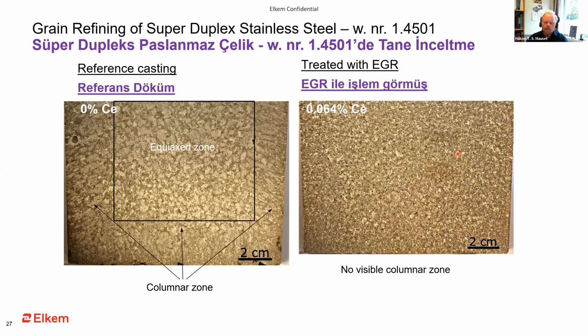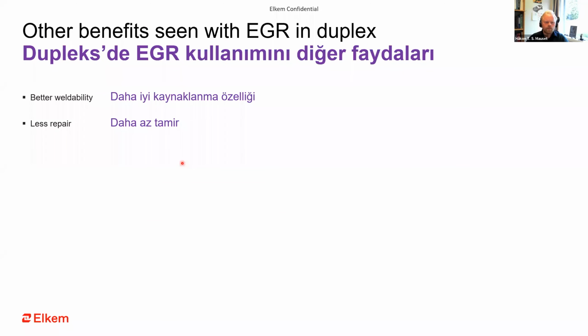While this is the one treated with EGR. Here you see we have 640 ppm of cerium in the steel, and there is really no visible columnar zone here. The equiaxed grains are much smaller than this one. So other benefits we've seen with EGR in duplex are better weldability and less repair welding on the castings.